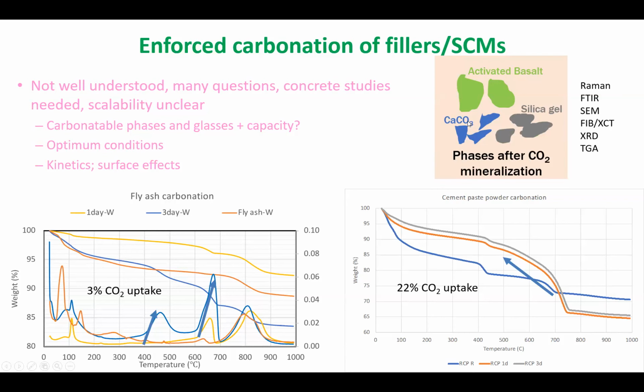So quantifying the CO2 uptake is not that challenging. Although, again, trying to explain why there are peaks at 400, you can actually see that this peak is overlapping with the calcium hydroxide peak. It overlaps with a couple of other things as well. So there is some uncertainty in the measurement. Better techniques, including evolved gas, etc., could improve the exact amount. But I mean, maybe it's not 22%, maybe it's 20%, right? We can get to that. That's not the major challenge.